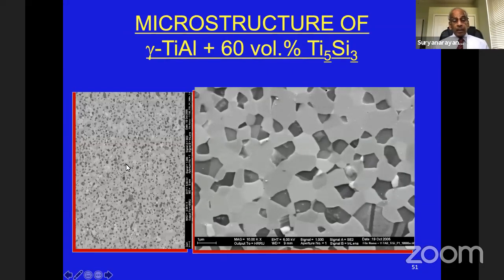Now, if you look at this, the microstructure is very, very fine. And now you can see both the titanium silicide and titanium aluminide, both of them are present. In gamma titanium aluminide, you can see twinning present. So the presence of these twins will indicate that this is the titanium aluminide grains and the others are the titanium silicide grains. So it's like a very small grain size of both the matrix and the reinforcement, and both of them are uniformly distributed. This is the type of microstructure which is conducive to formation of superplasticity.